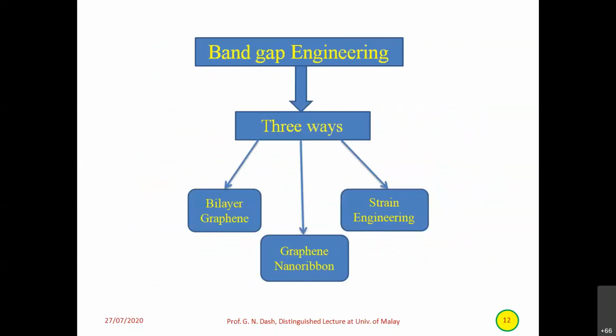See how we are going to engineer the band gap in graphene. There are three ways. If there is bilayer graphene and the two layers are given an electric field, then we produce some band gap. Then if you cut the graphene into small width, those are called nanoribbons. That means less than 50 or 40 nanometer width. We can cut the graphene into ribbons, then we can introduce band gap. And strain engineering, that means you can pull or stretch the graphene sheet, then of course it will develop some band gap also. So these are the three ways of band gap engineering.